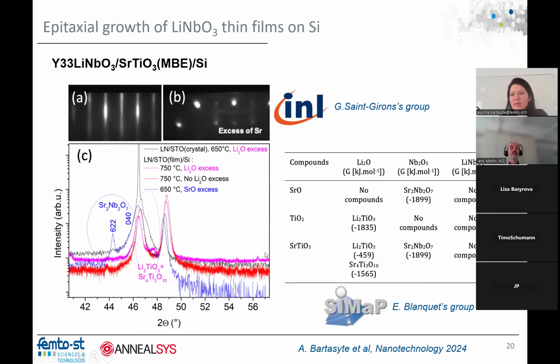So we first, in very early work, we tried to grow this orientation directly on silicon, and then used molecular beam epitaxy and a strontium titanate buffer layer, which is grown by MBE. It's a known template, which was used for barium titanate, PZT, and so on in the perovskite community. So it nicely grows with that orientation on strontium titanate.